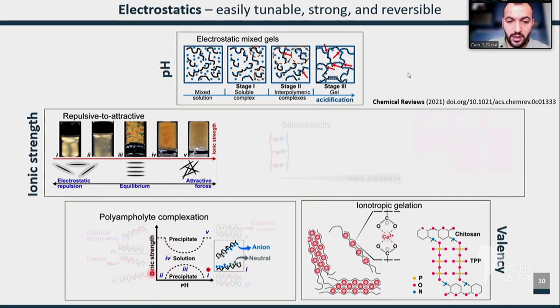So at low ionic strength and high pH, you have a solution, because one chain only sees the negative charge, the same charge of the neighbor chain, right? If we go down in pH a lot and we surpass the lower threshold of the pKa, then only the cationic blocks are going to be active. So positively charged chains see the positively charged chains on the opposite side, and they repel each other and they reach a state of solution. This is in low ionic strength. So I'm keeping the ionic strength fixed and just playing with pH.